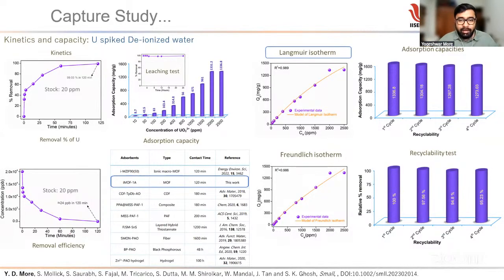What is the modern water system? It is a pilot scale where we give a deliberate, pre-calculated concentration of uranium, and then we standardize the adsorption capacity of our own MOF, how it adsorbs. We used uranium-spiked deionized water, where there is no other ion. We spike in a controlled concentration of uranium, so we know there is only uranium ion in this water, and we adsorb this uranium ion onto the activated MOF to learn the fundamental behavior in a non-polluted, non-competitive sample.